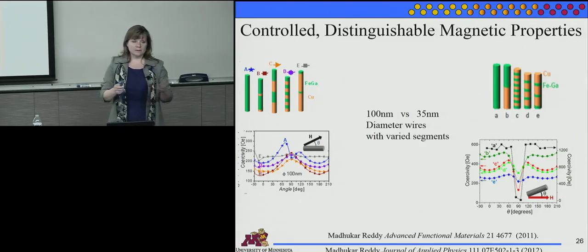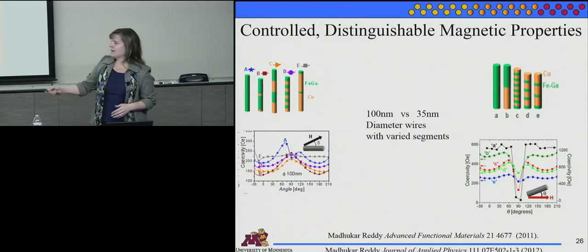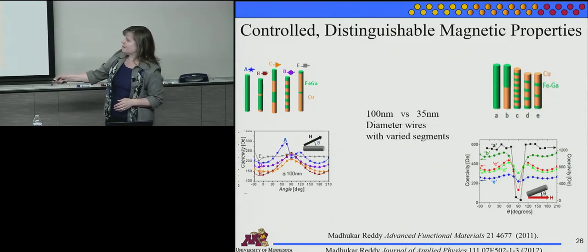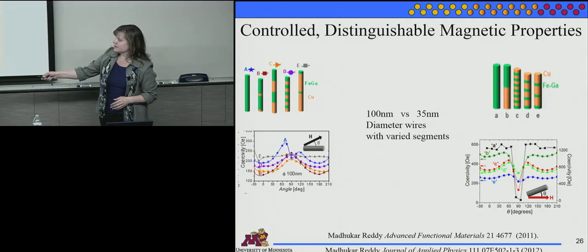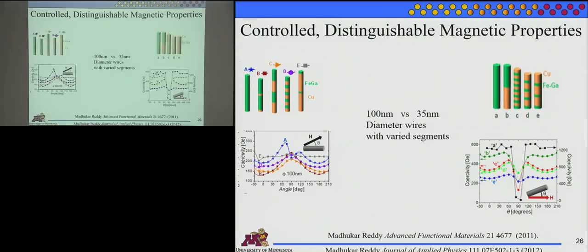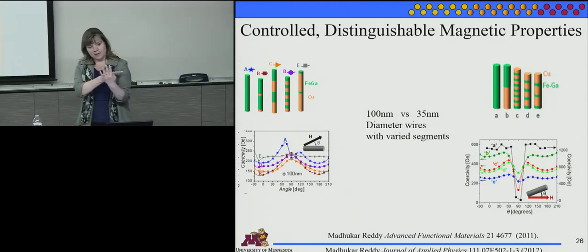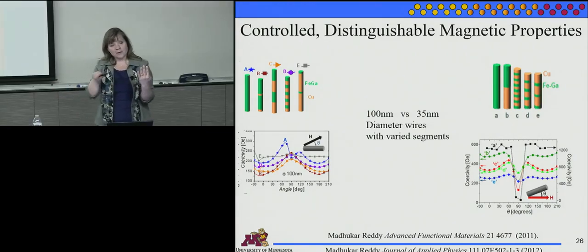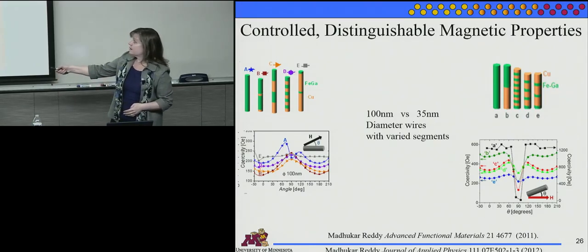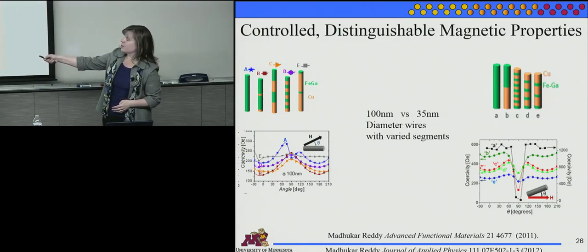And we have worked out why that happens. In this case, you get coherent rotation here, right? You have a minimum at 0 and 180, and you have a maximum at 90. You kind of expect that if the moments are just rotating around. You'd expect that when the wires are perpendicular to the field that you're applying, it's a little harder to rotate the moments. But those are for 100 nanometer diameter wires.